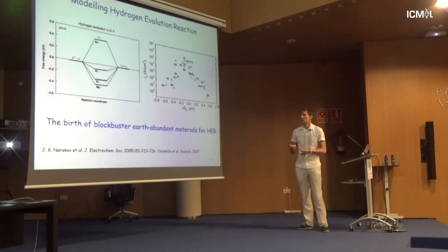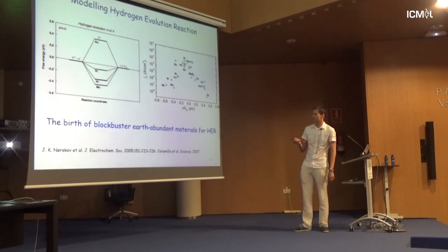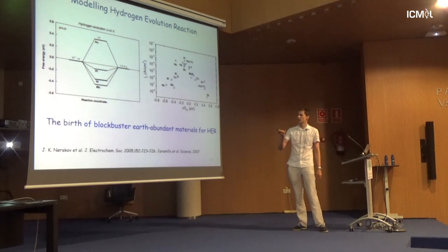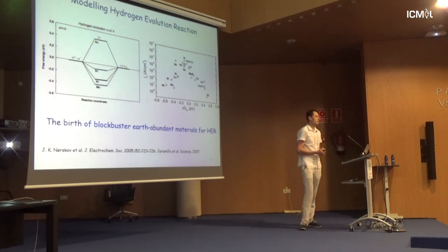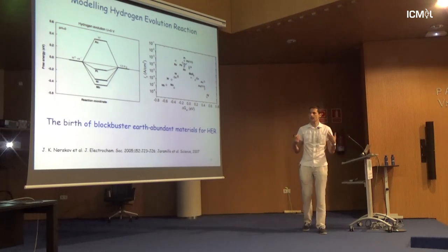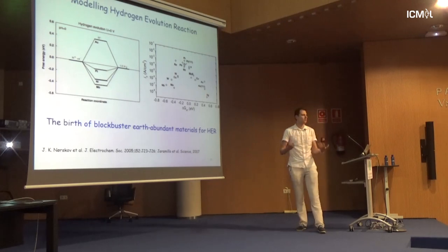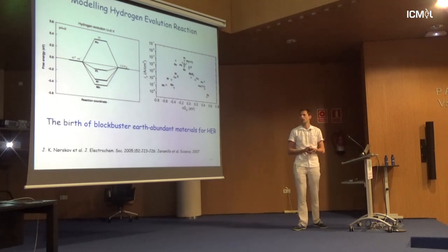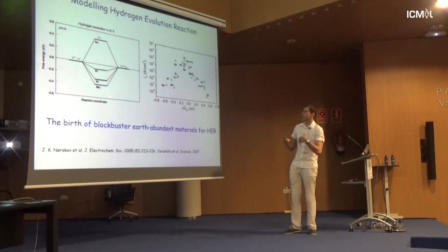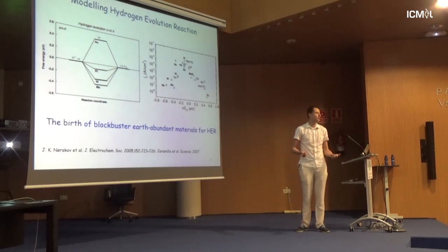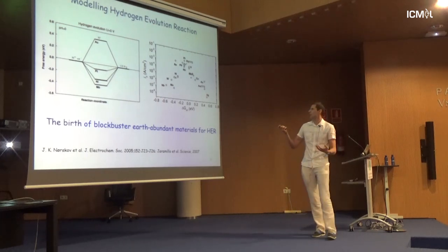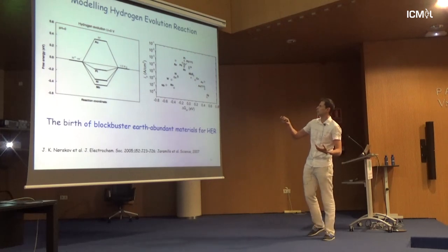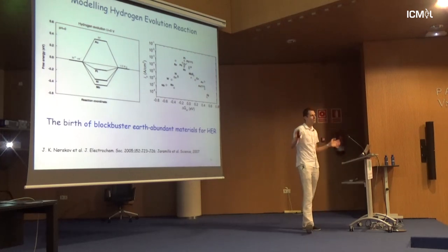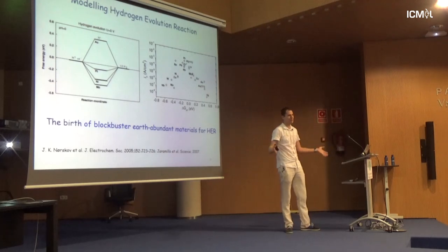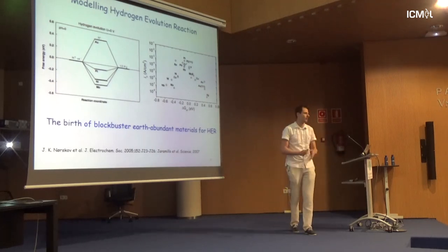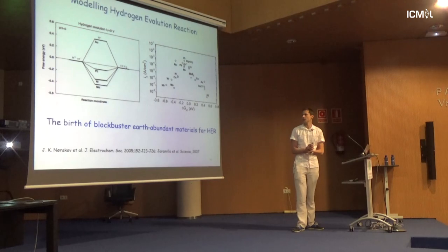And what you see is this free energy of adsorption is directly correlated with current density. So the correlation with current density gives you the indicator of what's going to happen. So you can put an extra layer of complexity as your computational power grows. You can add, for example, you can look not at platinum per se, you can look at specific layers in platinum and so on and so forth.